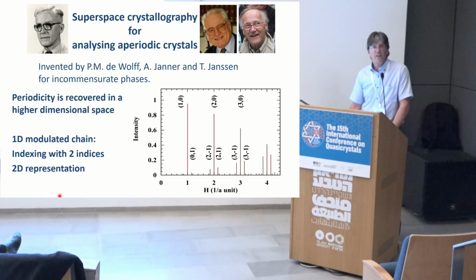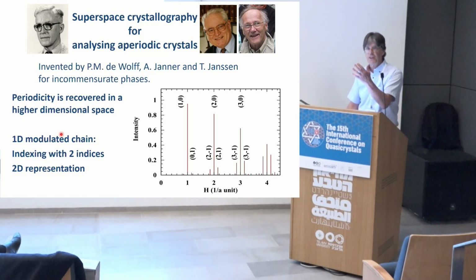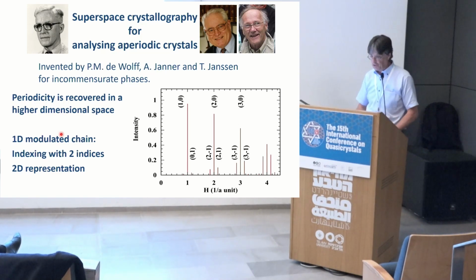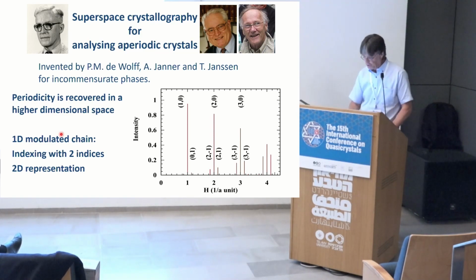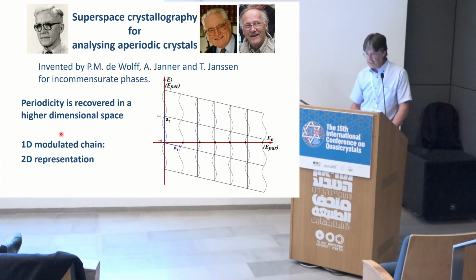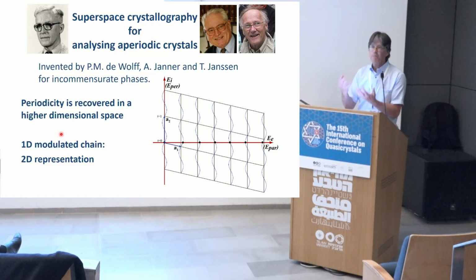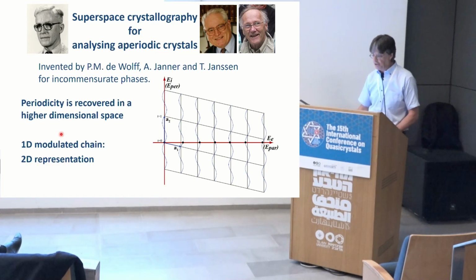And the trick they have been using is to recover the periodicity in a higher dimensional space. So from 1D, we go to 2D. For 3D, we go to 4D, and so on and so forth. I will not go into the detail, neither give a lecture on that, but it's just, for those who are not familiar, a kind of mathematical trick, so to speak. We lift everything into a two-dimensional space, and what was non-periodic becomes periodic and perfectly ordered, and that's the picture of the modulated chain I've shown you before.